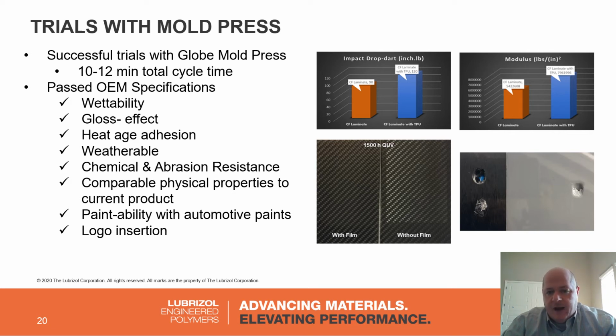That same exact height and inch-pound of force basically left a bump or indentation into the carbon fiber with film in the gray, but did not fully go through. You can see from the chart the increase in the impact drop dart test.